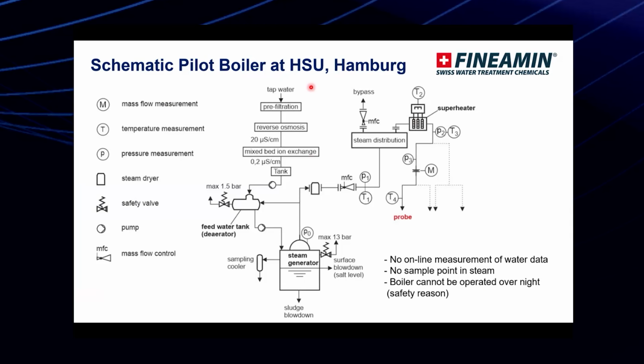Here, starting from the tap water, we do pre-filtration and then reverse osmosis and mixed bed. After that it goes to the feedwater tank, deaerator, and after that the steam generator. Then there is also a steam dryer, and then it goes to the mass flow control, and after that to the steam distribution, and then it will be reheated to superheated. This is the electrically heated boiler, and eventually the superheated steam will go out, and there is a probe where we have a metal specimen that will absorb the amine from the superheated steam on the piece of metal.